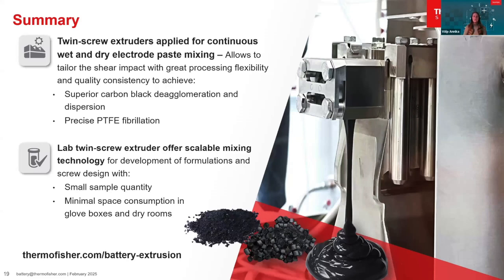I would like to highlight the following points. In manufacturing, twin screw mixers allow for the modification of shear effects by adjusting the screw design and processing parameters such as screw speed, temperature, and material throughput. When applied for continuous wet and dry electrode paste mixing, they provide great processing flexibility and quality consistency to achieve a superior carbon black deagglomeration and dispersion and good PTFE fibrillation and binder distribution. Continuous mixing also leads to high quality consistency, reduced downtime, and less cleaning effort.